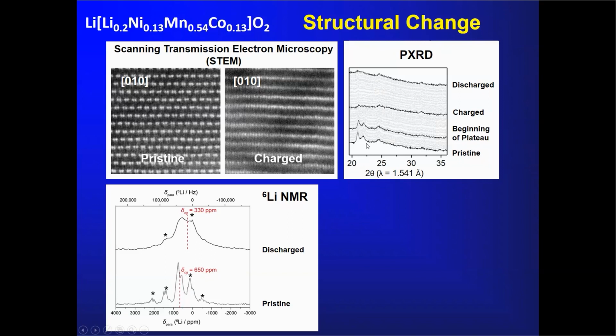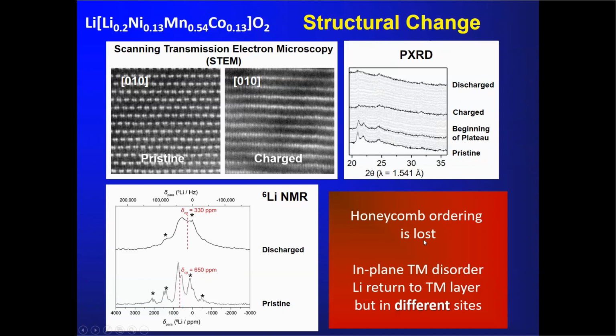So this all speaks to this irreversible change on charging. The message here is the honeycomb ordering is lost. There is largely in-plane transition metal disorder, and the lithium ions return to the transition metal layers, but in different sites from the sites that they were in before. Remember, you have lithium in the alkali layers and in the transition metal layers, and you remove both of those lithiums when you charge up across the oxygen redox plateau.